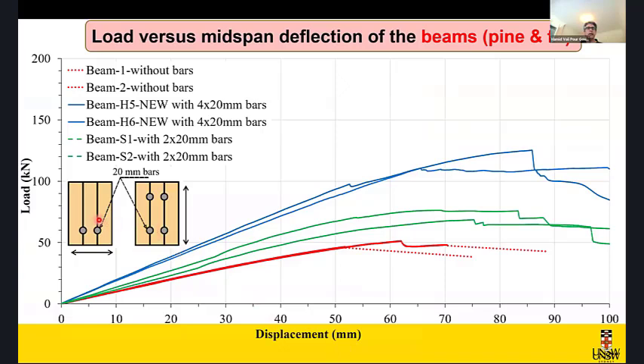So these are the 2 reinforced alternative beams we have tested, one with only reinforcement at the tensile zone, the other one in the compressive and tensile zone. And then, of course, the unreinforced alternative, the load displacement of the unreinforced one is the red one. The peak load is around 45 kilonewton with only reinforcing bars in the tensile zones. This alternative on the left, you see this green curve. The peak load comes up close to 65 to 70 kilonewton.